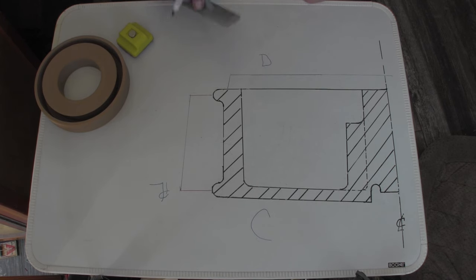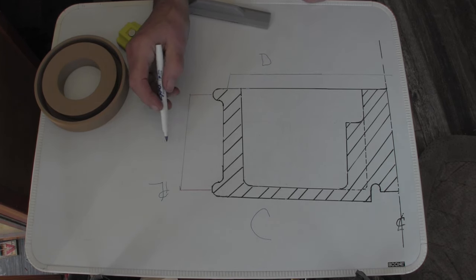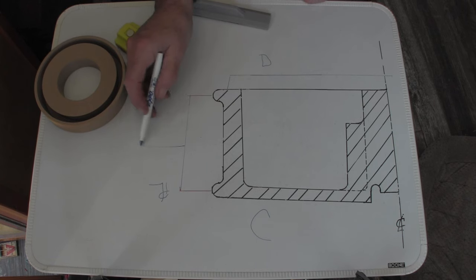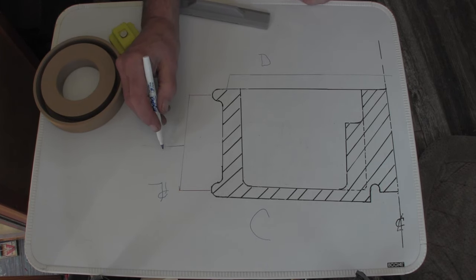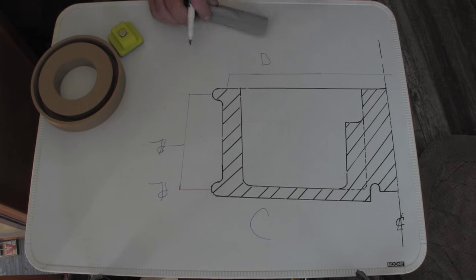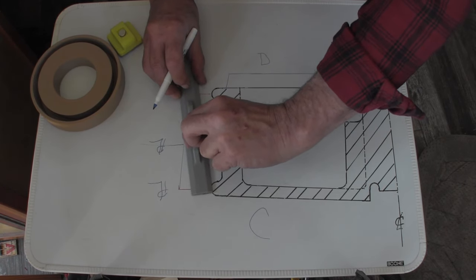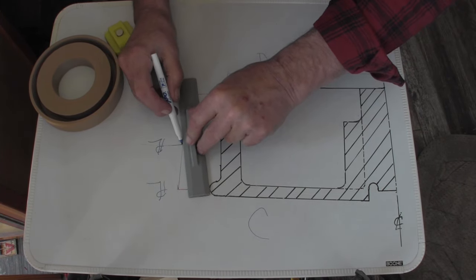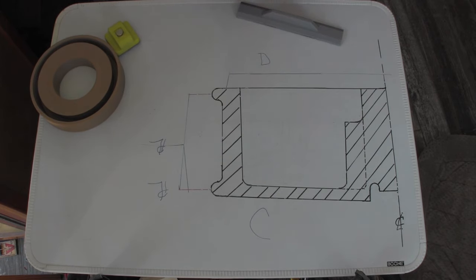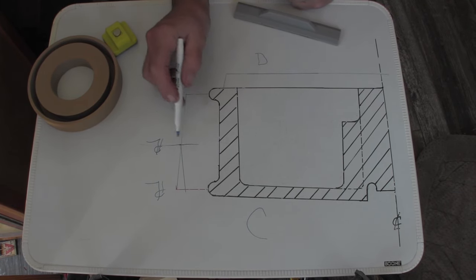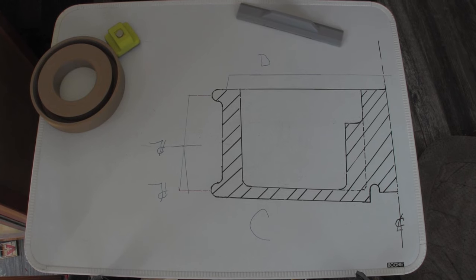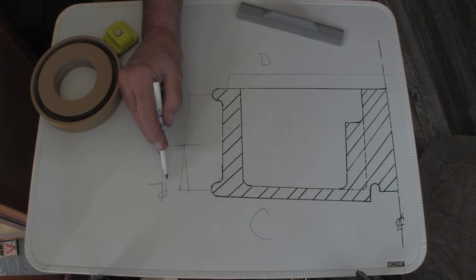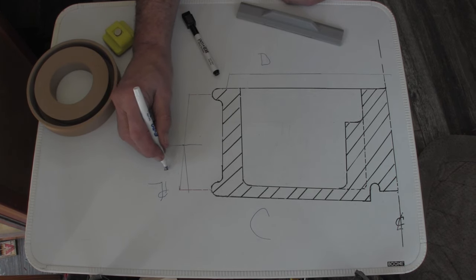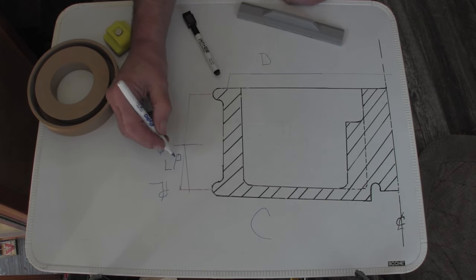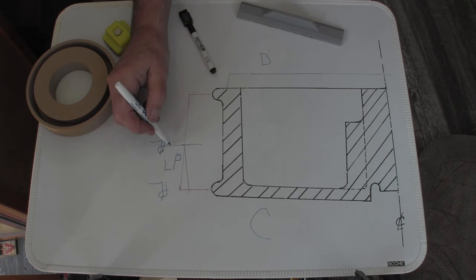You can also do this a different way, where if you don't like that, you want to keep the cope and drag somewhat equal. You can part that right there and make this the parting line. And you'd reverse the draft here. So from there to there, you'd have a split pattern like that. Parting lines there. Core would still be the same, except this would be this part here. This would be the loose piece. Okay. And that would be drafted that way.